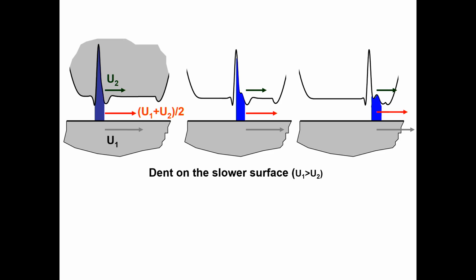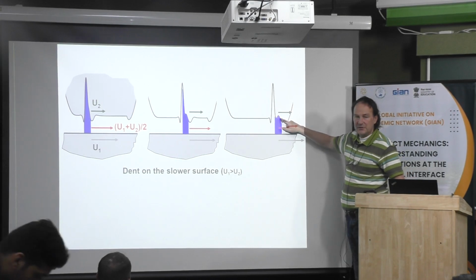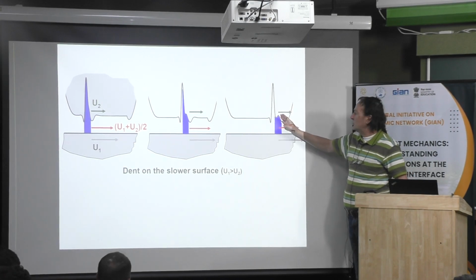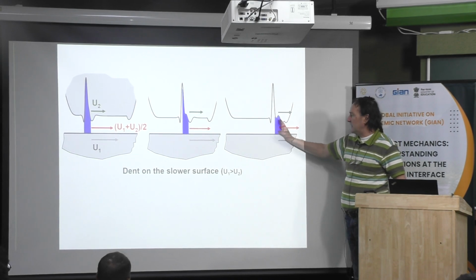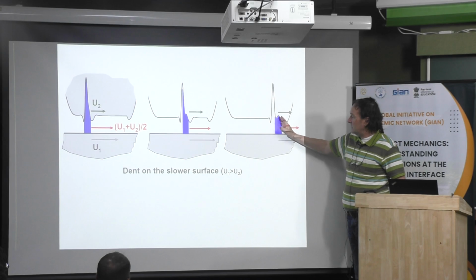This is the first one. Second one is that the lubricant is at a very high pressure. And then you remember, it's very viscous. It's in the glassy state. And because it is moving at the mean speed, when the lower surface is moving faster, it means that the pressurized oil will move ahead of the dent. And when it moves ahead of the dent, like that, it will generate a peak of pressure ahead of the dent. Okay? And that explains why you can damage the material in front of the dent.